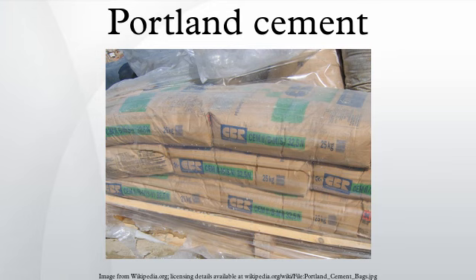This gives the concrete using this type of cement a 3-day compressive strength equal to the 7-day compressive strength of Types I and II. Its 7-day compressive strength is almost equal to Types I and II 28-day compressive strengths. The only downside is that the 6-month strength of Type III is the same or slightly less than that of Types I and II. Therefore the long-term strength is sacrificed a little.